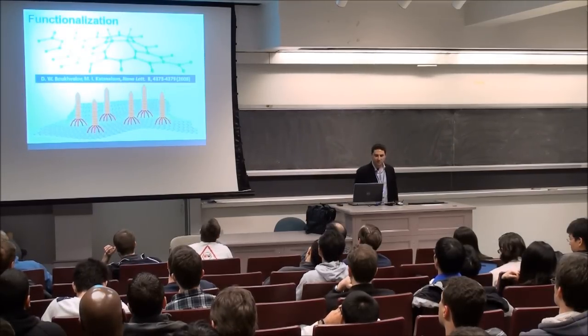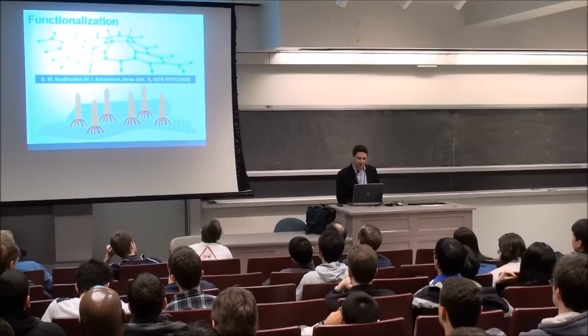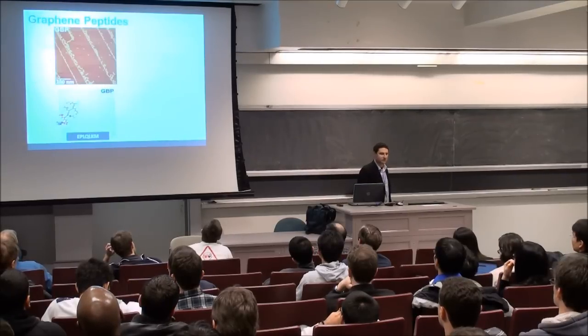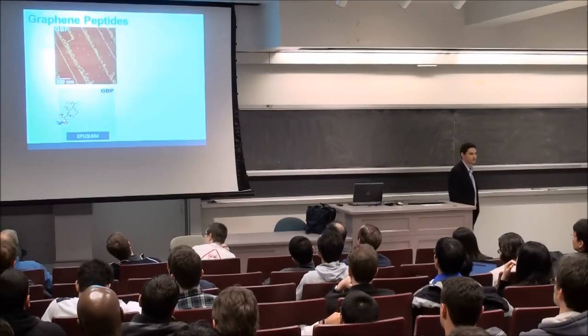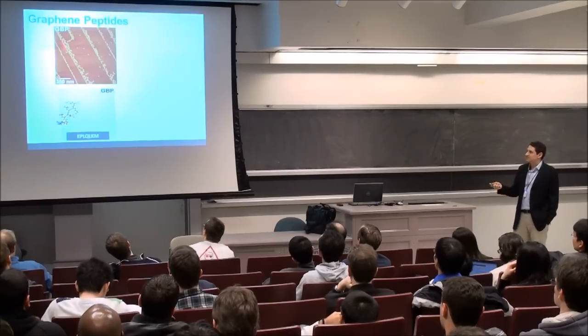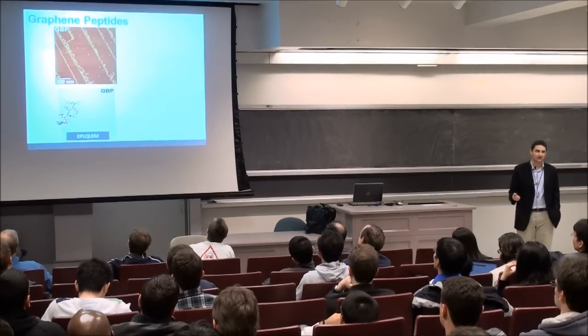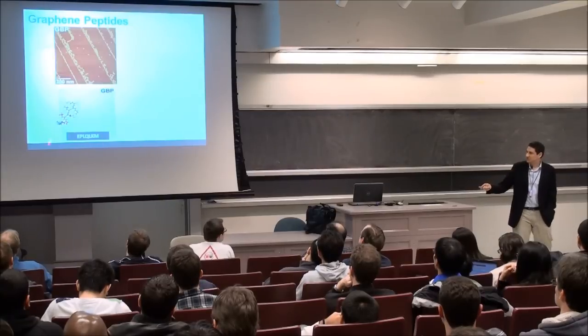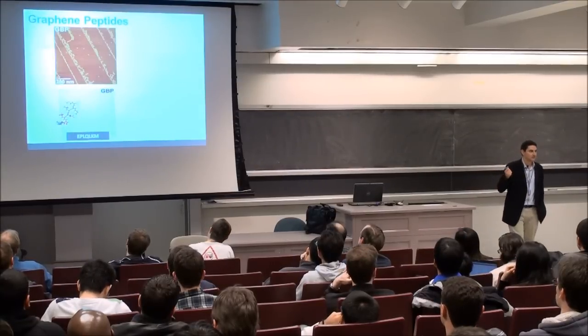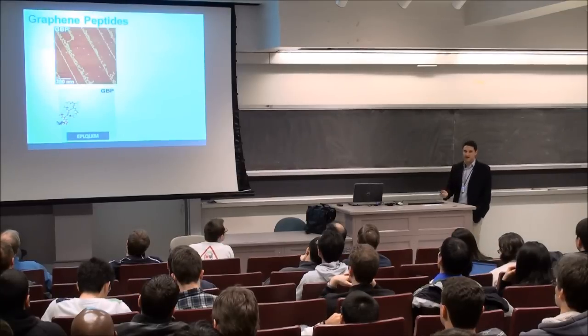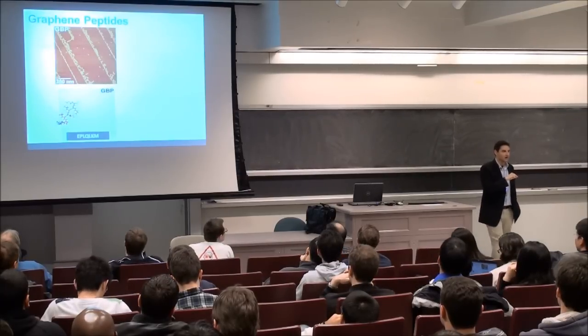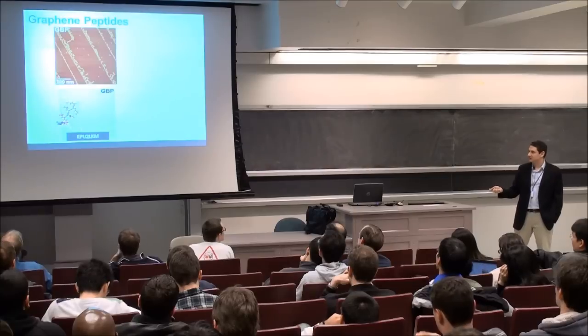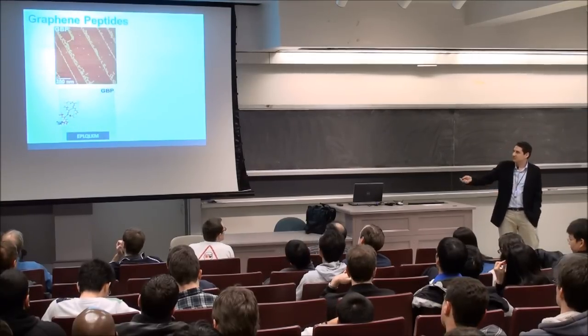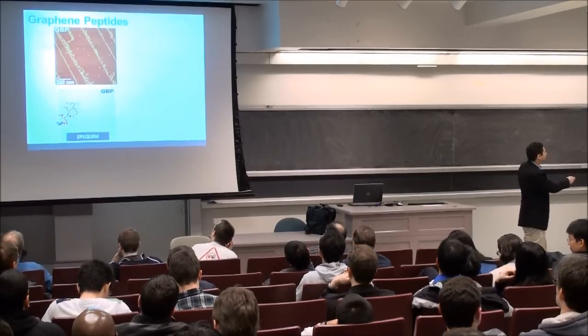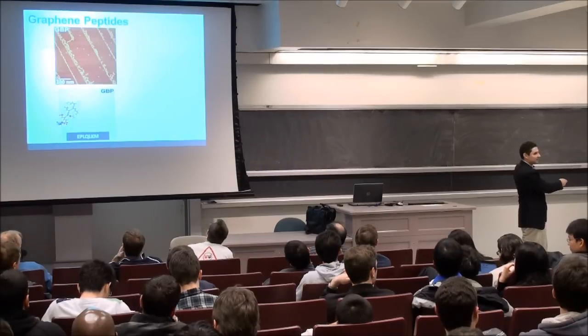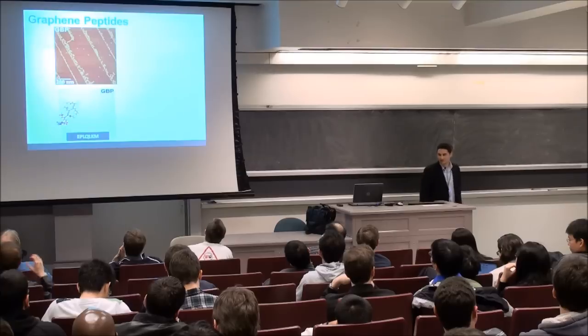So you're probably wondering, well, can you really get selective peptides that way? So we got some really interesting results that I wasn't expecting, which is that some of these peptides, this GBP right here, this is a peptide. We did some AFM experiments and some modeling here. It actually has this terminal, this is the sequence down here, it has this terminal glutamate there. It's negatively charged at neutral pH, so it actually will bind to the positively charged edge, the hydrogen terminated edge of the graphene here. So it will actually go toward the graphene edges. So if you look at this graphene sheet here, you can see the peptides actually line up exactly along the graphene graphite edges there, which I thought was pretty cool.